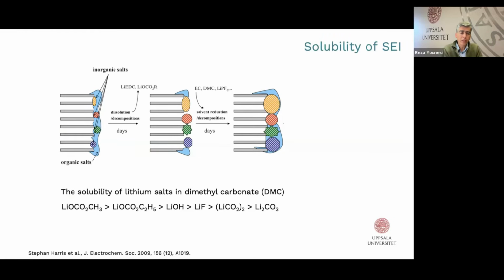This is one very interesting example published by Stephan Harris a few years ago, highlighting this issue: if you look at different SEI species in lithium-ion batteries, you could measure their solubility in, for example, DMC solvent, and see that they have different solubility. Ideally, your SEI should be formed by a species that have very low solubility in the solution, so you could use some electrolyte and tune it to form species that are less soluble.